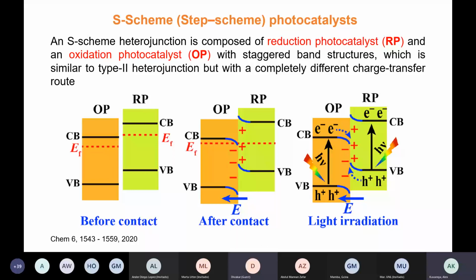So the bending type in this kind of photocatalyst will allow the electrons that are generated in the reduction photocatalyst to remain there, whilst the holes that are generated in the oxidation photocatalyst remain there. The only charge carriers that will combine are the electrons in the conduction band of the oxidation photocatalyst and the holes in the valence band of the reduction photocatalyst. So in that process, you again have extended lifetime of the electrons in the reduction photocatalyst and the holes in the oxidation photocatalyst to drive these reactions.